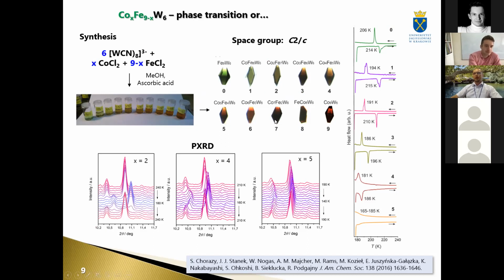grow from this solution. And starting with powder X-ray diffraction and DSC data, we can see the phase transition with thermal characteristics which are composition dependent. Also, the type of transition, I mean first order or second order, can be observed depending on the composition. For example, for iron-rich complexes, we have quite sharp transitions, which can be seen also here. But when we decrease the amount of iron and increase the amount of cobalt, the transitions become less steep and finally vanish.